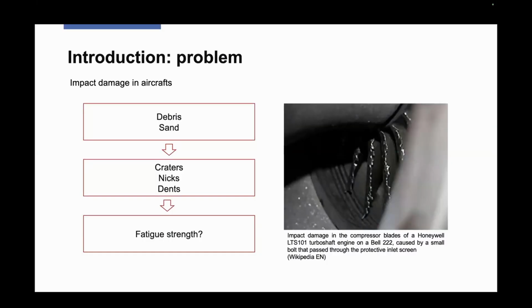So first of all, impact damage is a big concern for many applications, and in particular for aircraft engineering, aerospace engineering. There is a typical expression in this sector that is foreign object damage. It means that there are some particles, debris, sands, they say also rivets, that are on the piste and that can be ingested by the engine during takeoff, landing, also birds. So the problem is that we have the appearance of craters, nicks, dents, and other defects that can propagate and reduce the fatigue strength, causing also some disasters.